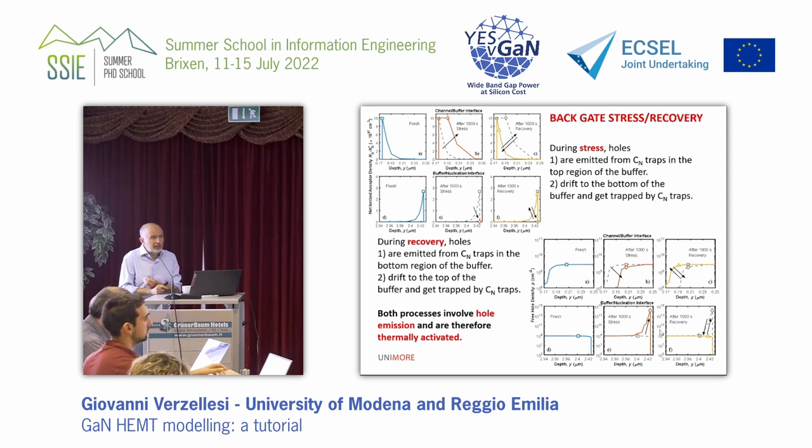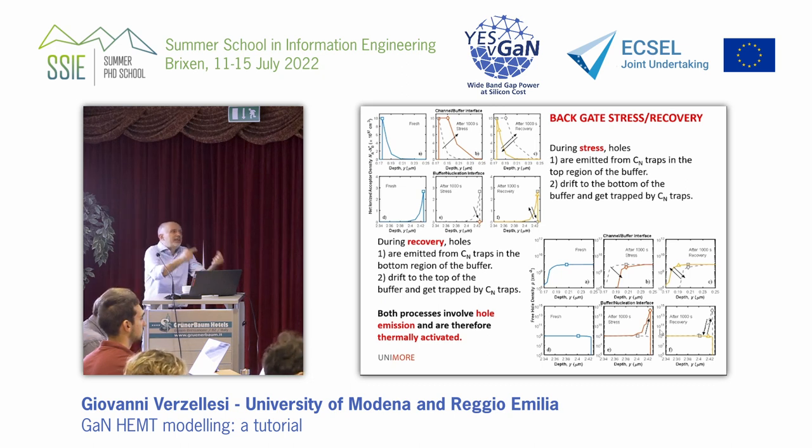Also, the recovery transient shouldn't be thermally activated, I mean, within the framework of the model, it should be related to trapping that is not thermally activated for a standard point defect trap, but also this process needs hole emission. Before being trapped, holes need to be emitted in another part of the device. So the bottleneck in terms of times and thermal activation is in both processes the hole emission process.